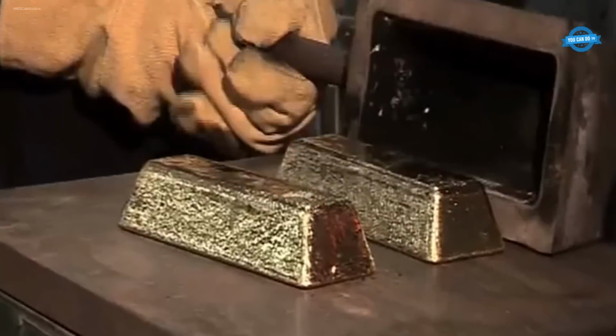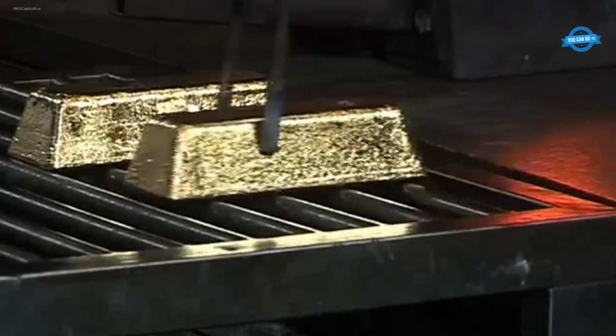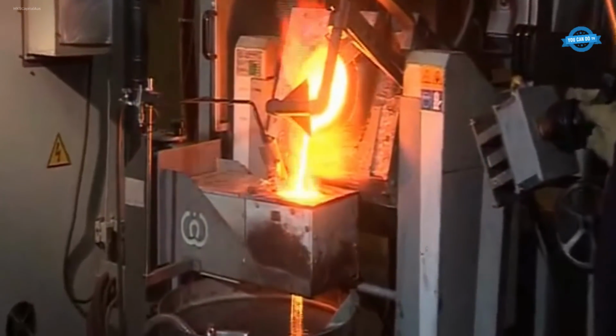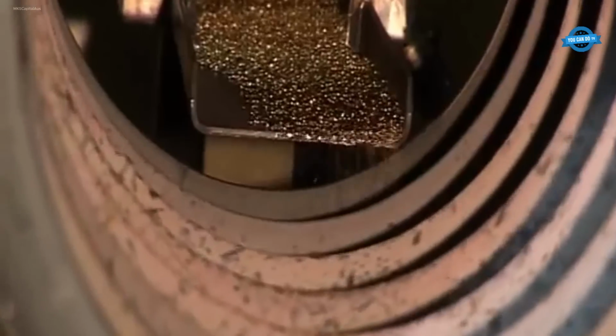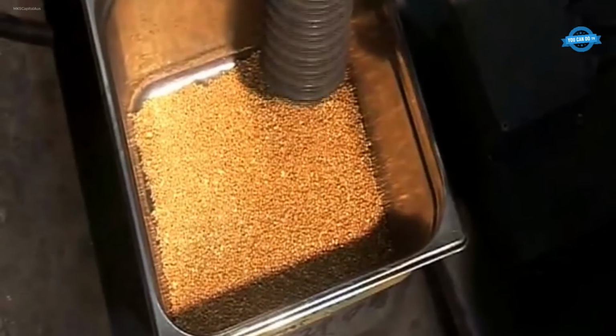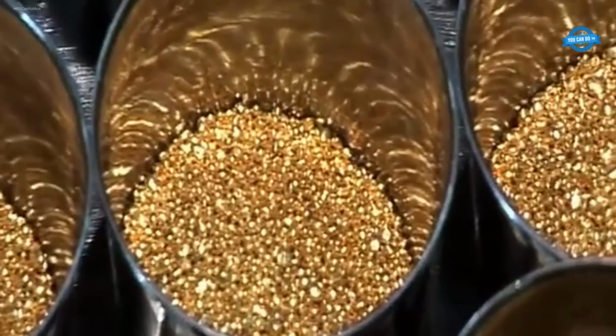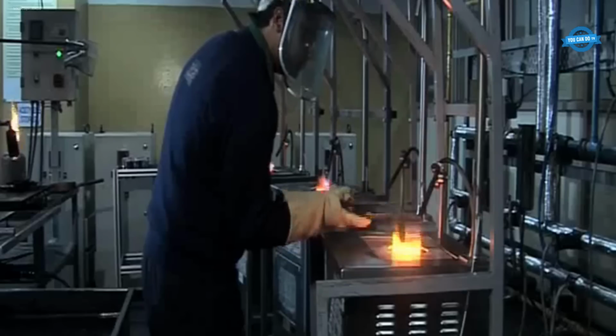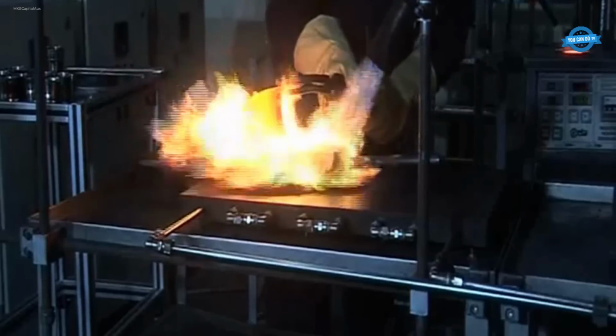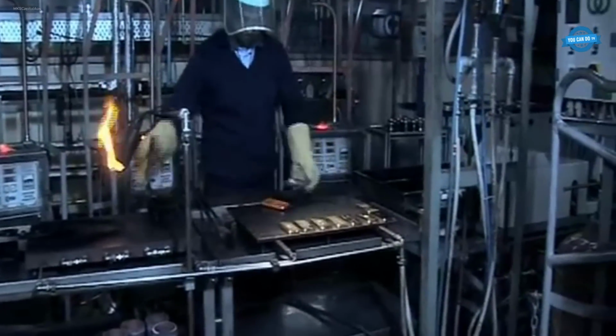Impure gold is cast into anodes and refined via electrolysis, depositing 99.99% pure gold sponge onto cathodes. This sponge is then washed, dried, and formed into grains or bars. A CNC-controlled stamping press ensures precision serial numbering, with weight captured by Mettler Toledo scales directly into the inventory system.